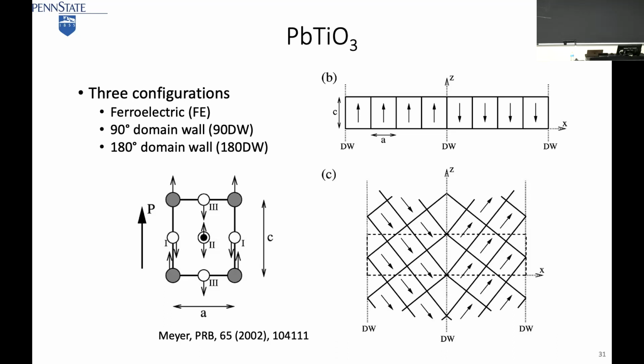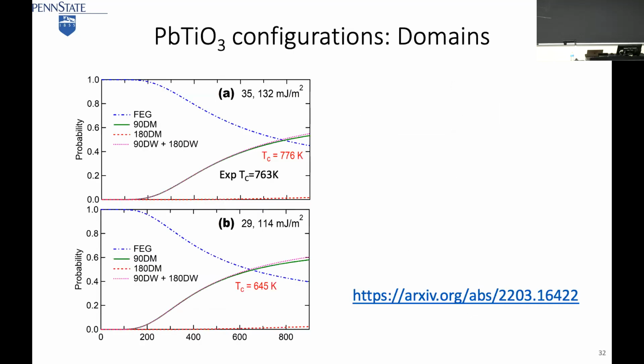So, of course, people are already calculating the domain one energy. Of course, different literature calculations will be different. So we take two sets of data, and we believe this data is more accurate, even though it's older. We predict the transition temperature of 773.6, and the experiment is 763. Again, there's no fitting in the model, but you have to get a configuration.